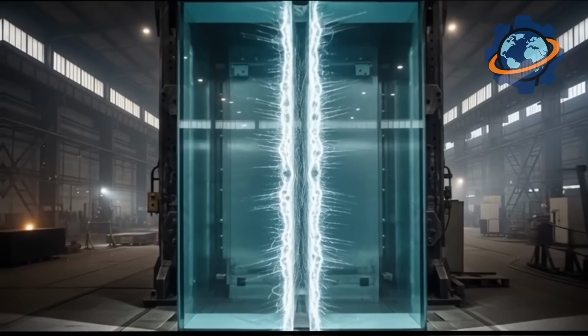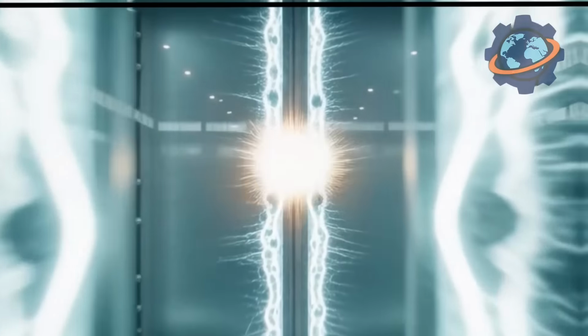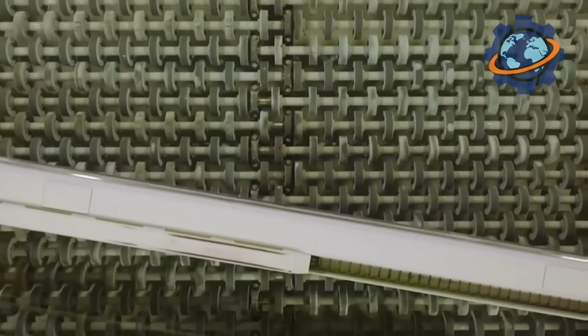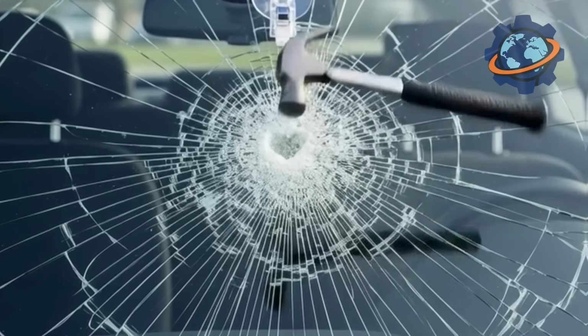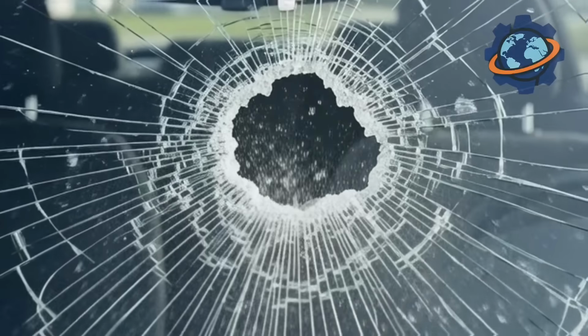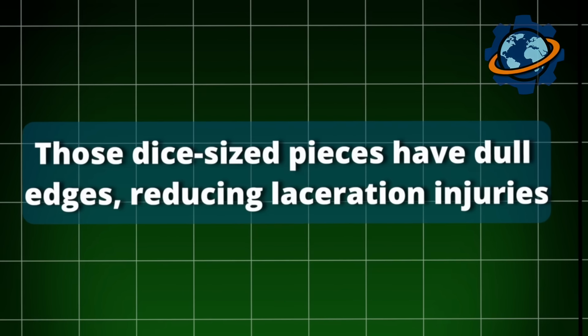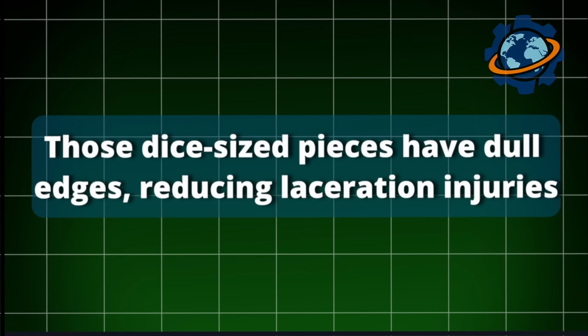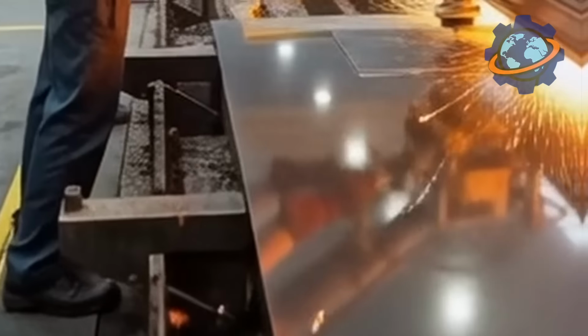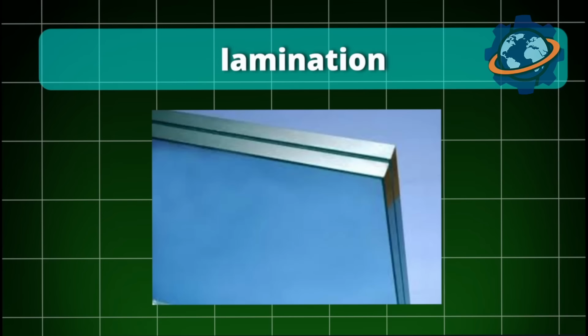This creates locked-in stress. Outer surfaces compress, while the interior stretches, like a tightening rubber band inside a rigid tube. The tension is enormous. Tempered glass achieves 4 times the strength of regular glass. But here's the crucial part. When stressed beyond limits, that internal tension explodes the glass into thousands of small cubes. The pattern isn't random, it's designed. Those dice-sized pieces have dull edges, reducing laceration injuries. One safety engineer puts it bluntly, tempered glass doesn't cut throats. That's the whole point.